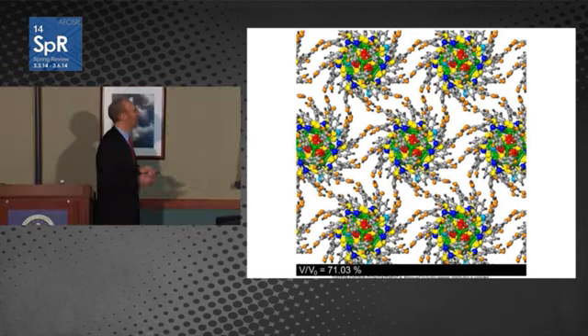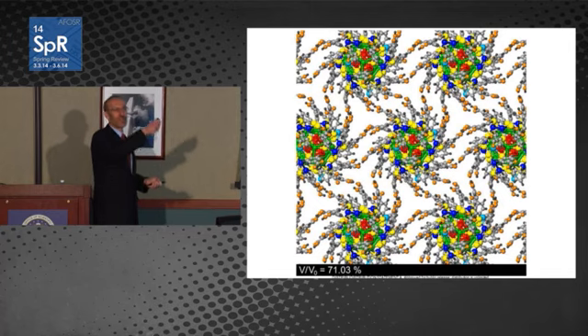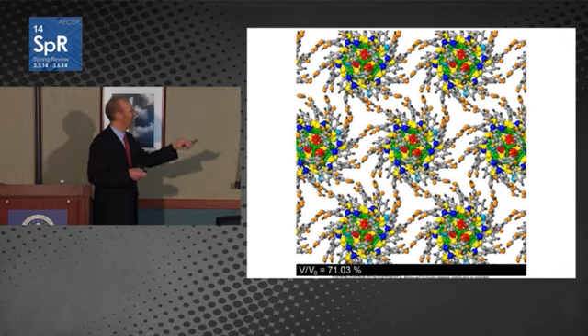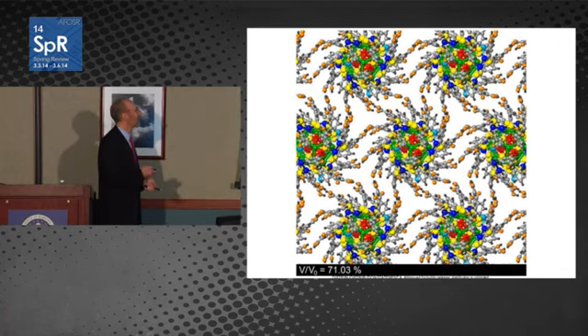That can give us an interesting energy dissipation method. And this material has a negative Poisson ratio. When you stretch it, instead of getting thinner, it expands as a result of kind of these kinks in these ligands as we compress it. So interesting materials.